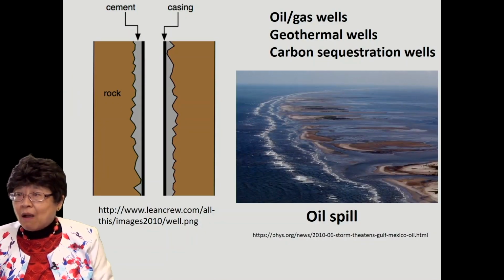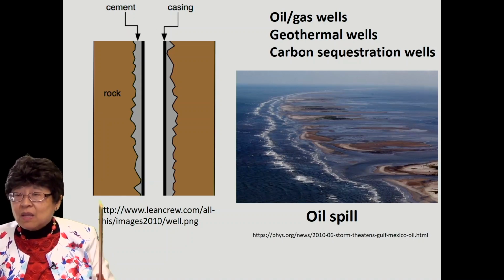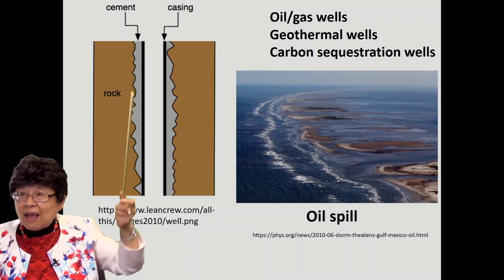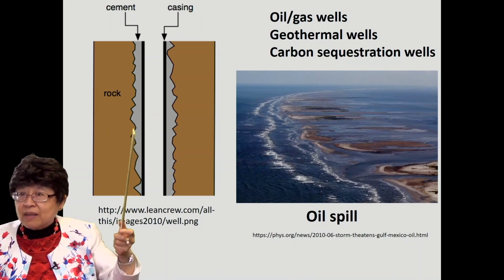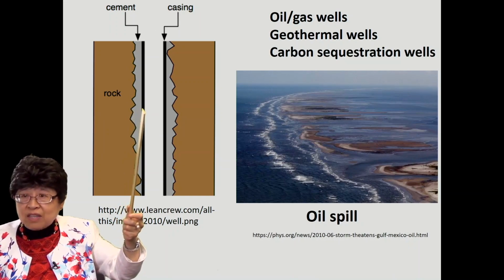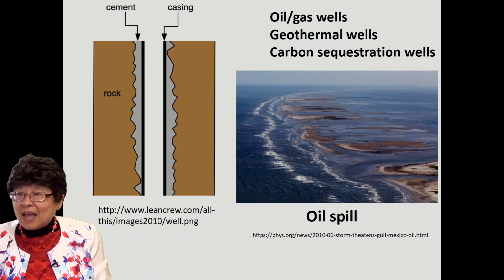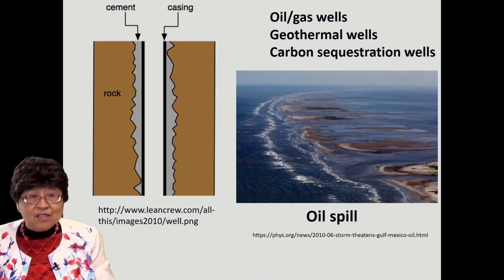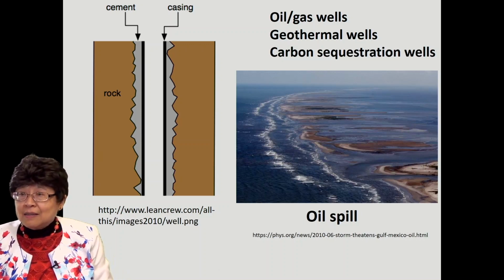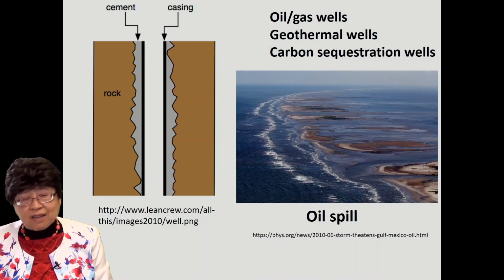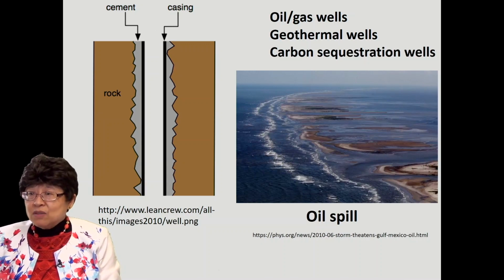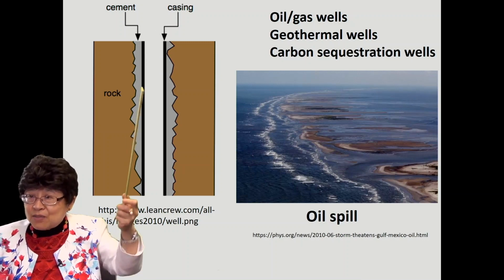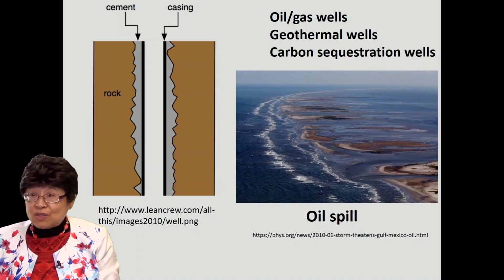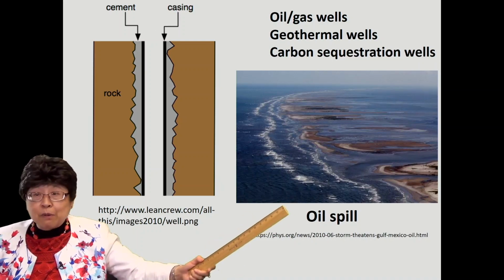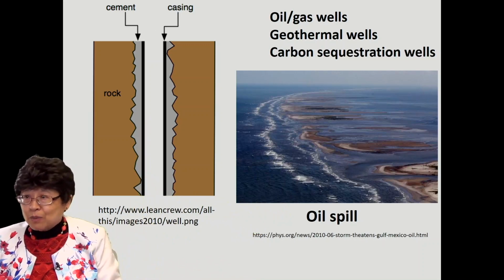And there are oil and gas wells as well as geothermal wells and carbon sequestration wells. And all these wells require the sealing of the well, and cement is used for the sealing. In this drawing, it seals the interface between the steel tubing called the casing and the rock. And the cement sees a lot of pressure there, and it's important to sense that pressure. You know, stress and strain are just two sides of the same coin, and so one can use the smart cement for the cement sealing here so that it becomes able to sense. Oil spill is a terrible thing that can happen if the sealing is not working.